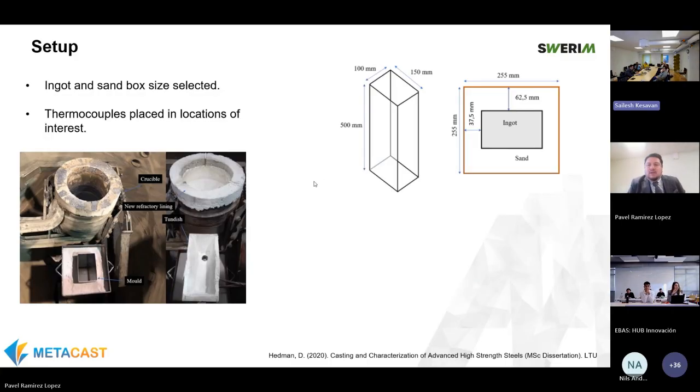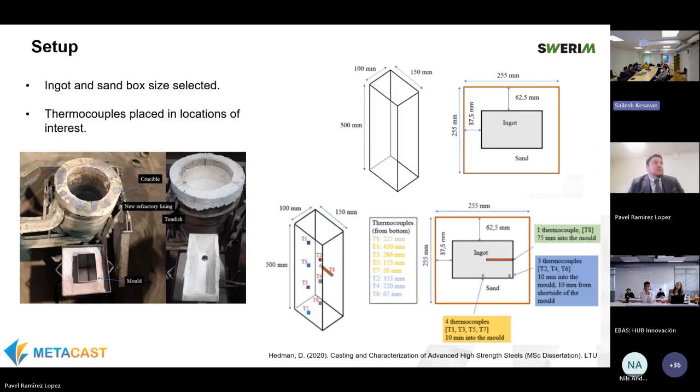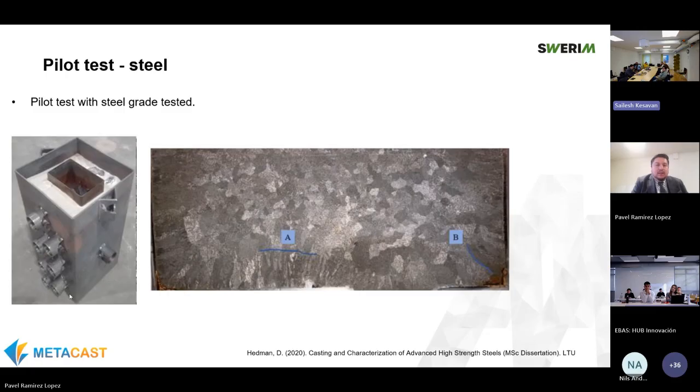These are the dimensions that you see here. And what was most interesting for us is to add through holes in this plate, and you can see them here. Through holes in this plate, we were able to implement thermocouples, not only on the surface, but actually inside the ingot as it solidified. So we were actually capable of tracking the temperature inside the ingot during the whole solidification process. Happily, since we had done this pretest, everything went well.